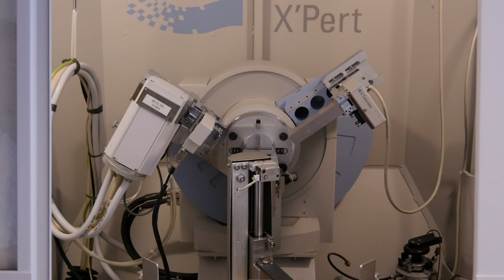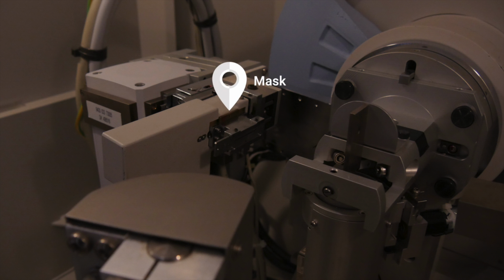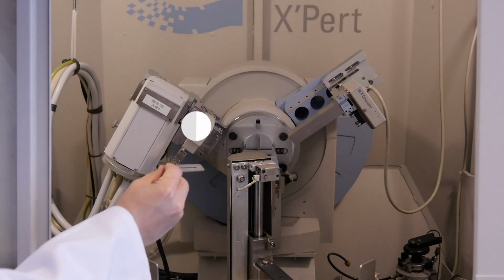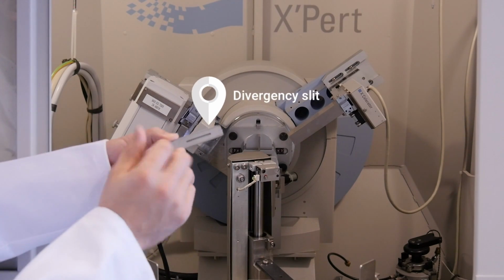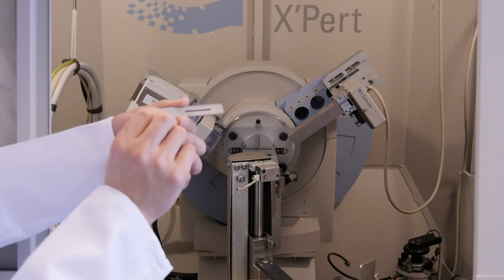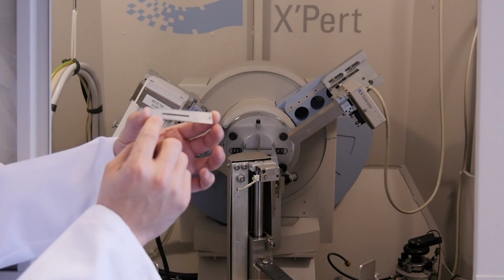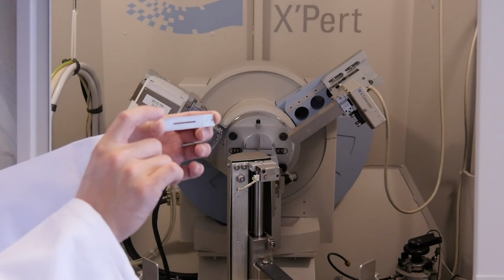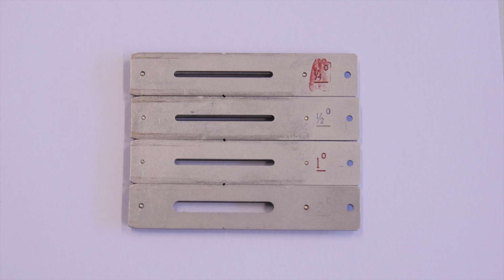The set of metal plates called the Soller slit removes the most diverging X-rays, leaving the more parallel X-rays to pass. A mask is used to control the length of the X-ray beam, which is related to the size of the sample holder. Another important slit, called the divergence slit, is used to control the width of the beam, which is related to the angular resolution of the pattern. The smaller the divergence slit we use, the higher the angular resolution. However, the intensity of the diffracted X-rays will decrease when a smaller divergence slit is applied.